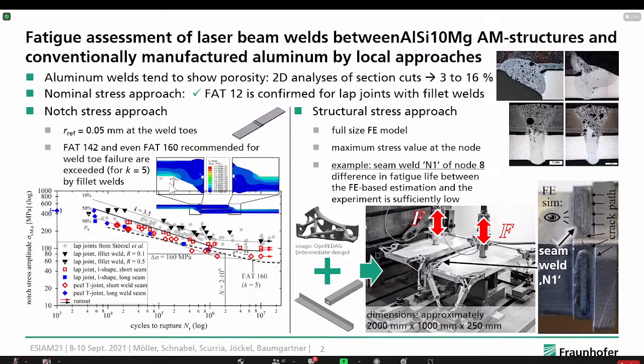As a solution, you can have models which are based on the experimental data on simplified cases, and then add a factor, let's say an increasing factor for the stresses, depending on the defects that you have. And that defect size can be obtained, for example, with CT scan. So you don't need to do the testing and figure out where on the fatigue plot your data is approximately located.